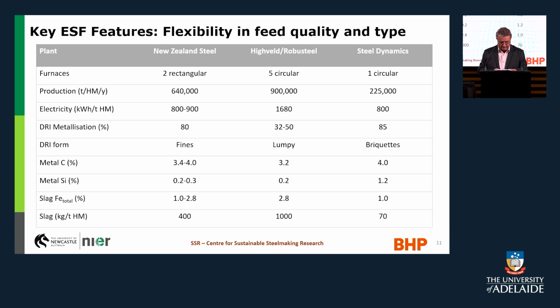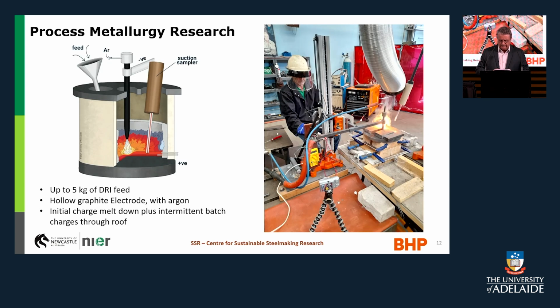Last key point here is that we can handle a big slag volume. So if we've got lots of gangue in the ore, we can handle the slag quantities. So typically New Zealand Steel, 400 kilograms per tonne hot metal. Highveld was at 1,000, and Steel Dynamics is quite a special operation. They run around 70. So there's a lot of interest.